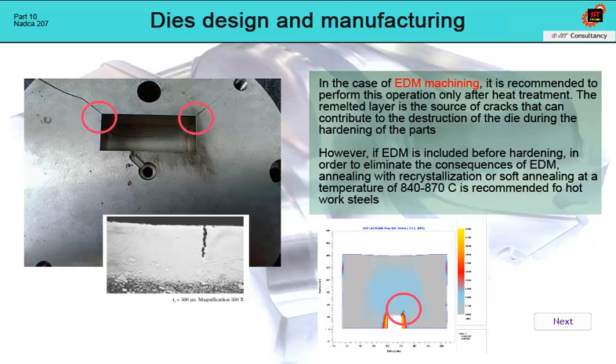The designer should also think about this situation and mark on the drawing the places machined by EDM and the places from which the remelted layer must be 100% removed. It should also indicate whether EDM is performed before quenching on the annealed material or after quenching. The technologist should then determine when and what kind of annealing process will be included.